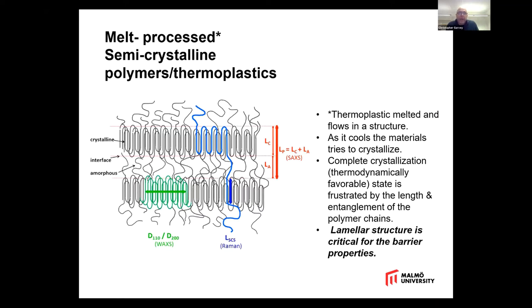And at a molecular level, the material is starting to crystallize, which is the thermodynamically favorable state. In fact, complete crystallization is the most thermodynamically favorable state. But if you think of this as a big ball of spaghetti, long flexible polymer chains, the entanglement of the different polymer chains results in a situation where it cannot crystallize completely. And this is a very important concept for these materials, both in terms of their processability, in terms of what kind of mechanical properties. So for example, those fibers that I showed you at the start of my talk, these very high-end fibers, they're not made from melt processing. And the fundamental insight of that process is to get them to crystallize as much as possible.